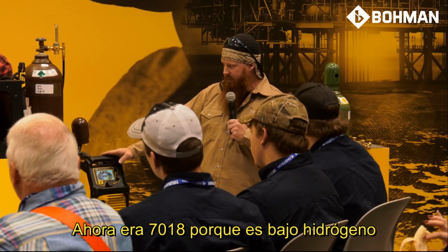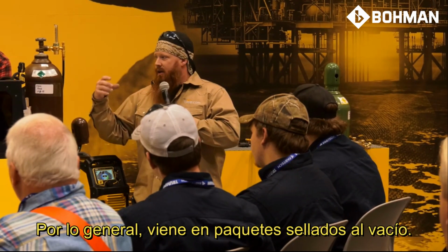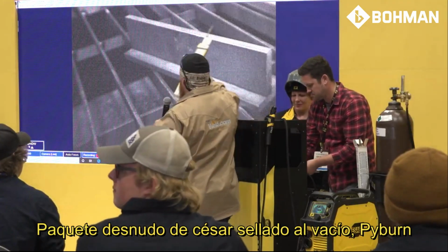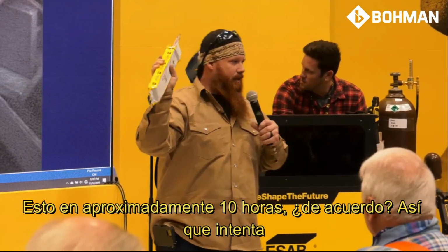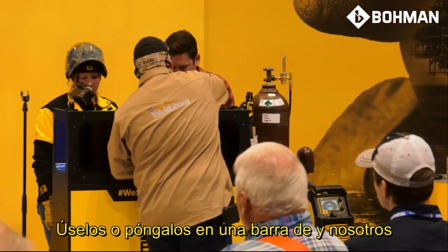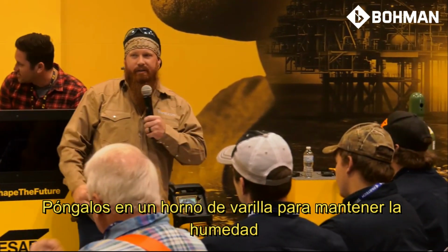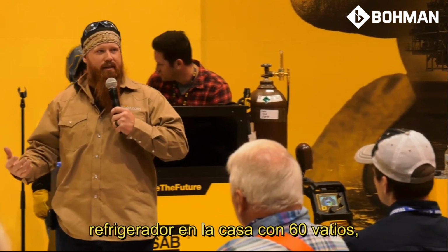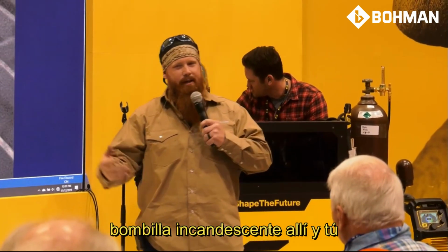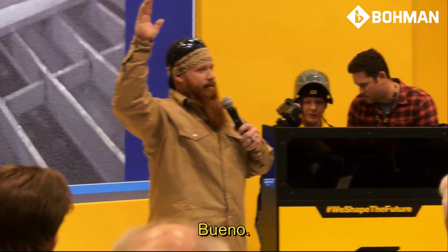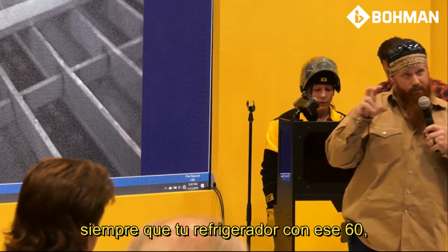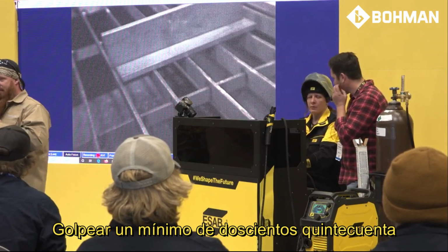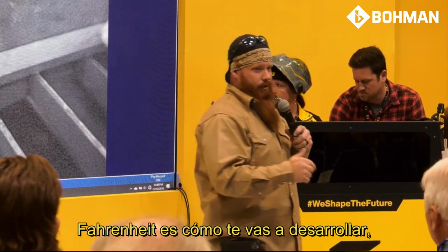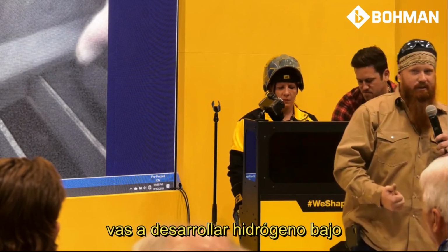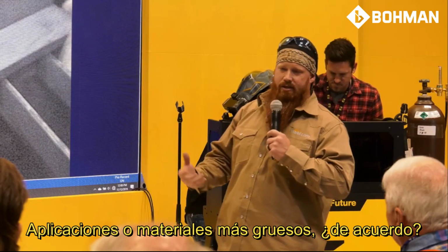Now with 7018, because it's a low hydrogen electrode, it usually comes in these vacuum sealed packs. So these are vacuum sealed packs. You should probably burn this up in about 10 hours. Try to use those up or put them in a rod oven. We put them in a rod oven to keep the moisture out. How many of you have a refrigerator at the house with a 60-watt incandescent light bulb in there, and you say, I'm keeping the moisture out? Good answer. Because if that refrigerator with that 60-watt light bulb in there is not hitting a minimum of 250 degrees Fahrenheit, you're getting moisture into your electrodes. You're going to develop porosity, you're going to develop hydrogen under bead cracking, and you don't want any of that, especially if you're dealing with structural applications or thicker materials.